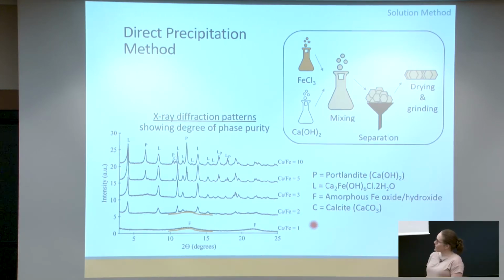Now, if you increase the ratio to 2 for the solutions that you mix together, then you do end up with this peak, which is the layered double hydroxide, but we still have this amorphous phase present. If you go to 3, we're starting to get rid of that amorphous bump, and we still have the layered double hydroxide. If you go up to 5 and 10, we actually end up with what's known as Portlandite, one of the starting materials, still in the system. So we want to obtain phase-pure LDH, and it looks like a ratio around 3 is what we need, but the question is why?